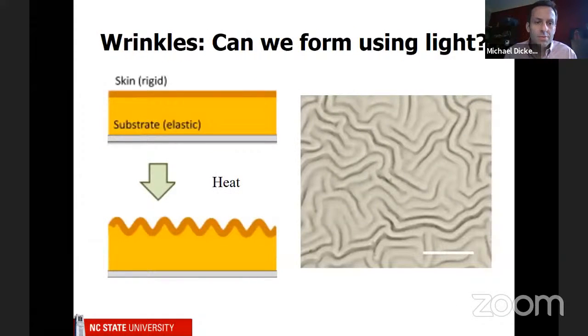Let me go back to this cartoon, this one. The things that matter in terms of dictating the periodicity are the thickness of this rigid layer, which I haven't labeled, but people would usually call that H, and then the modulus of the substrate and the modulus of the top layer. So to get the wavelength to be smaller, you would want this rigid film to be thinner. The idea is that in terms of bending energy, the thinner the film is, the easier it is to bend. The minimum energy for any kind of bending would just be one mode like this. But you have multiple modes because that film is attached to that substrate.